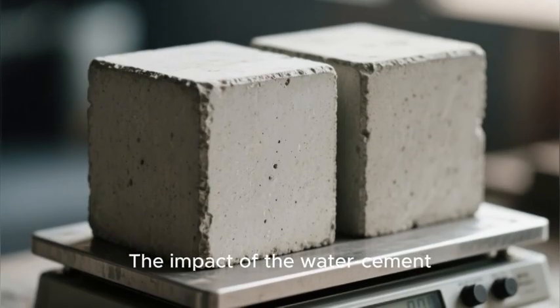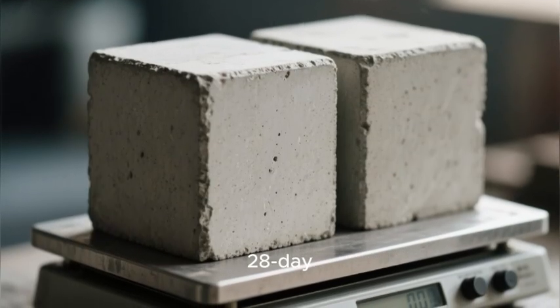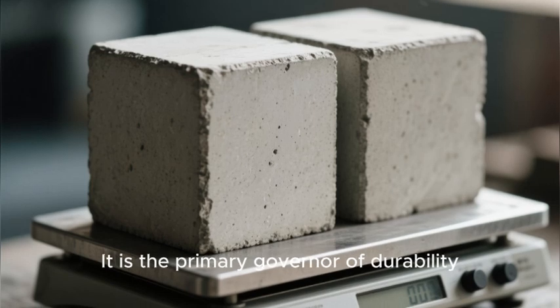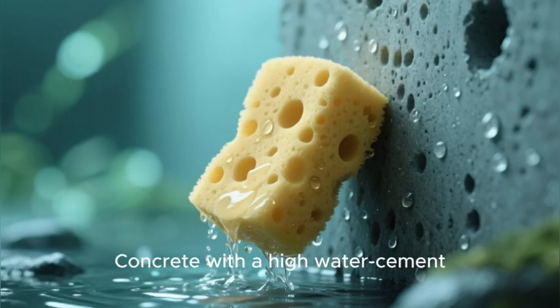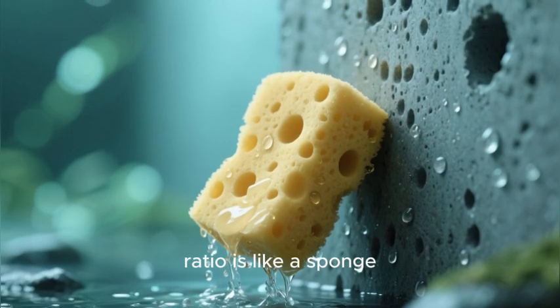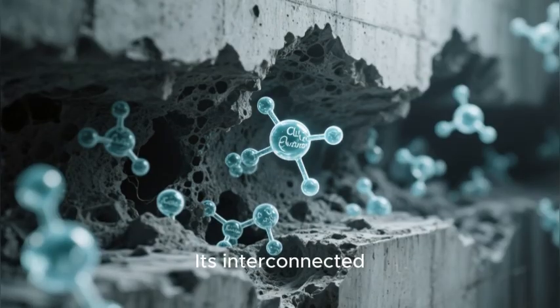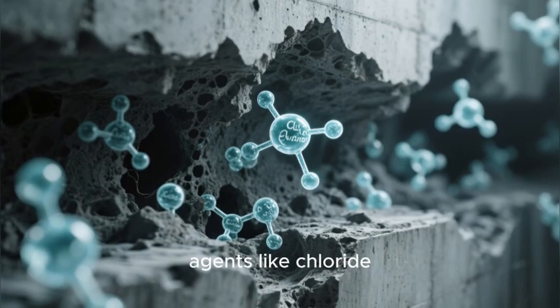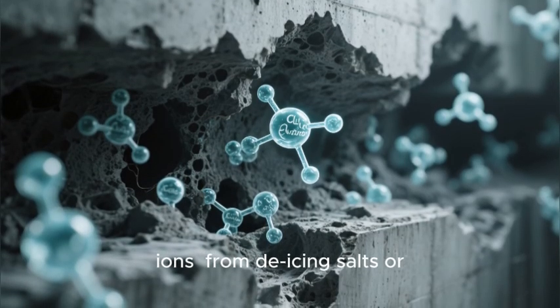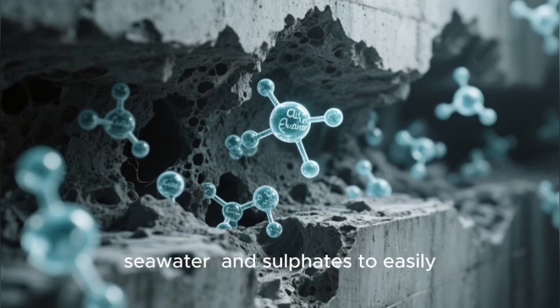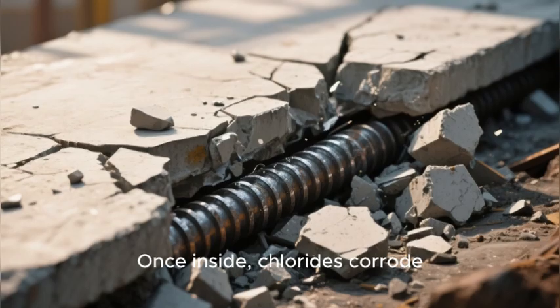The impact of the water-cement ratio extends far beyond 28-day compressive strength. It is the primary governor of durability. Concrete with a high water-cement ratio is like a sponge. Its interconnected pore network allows aggressive agents like chloride ions from de-icing salts or seawater and sulfates to easily penetrate the concrete. Once inside,